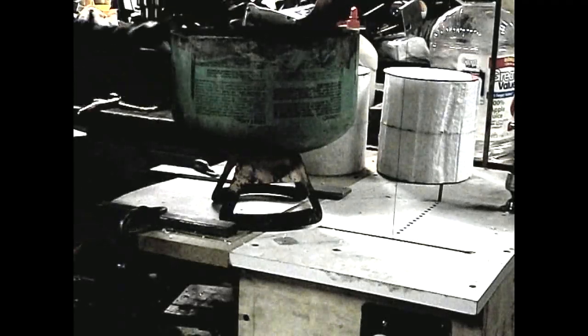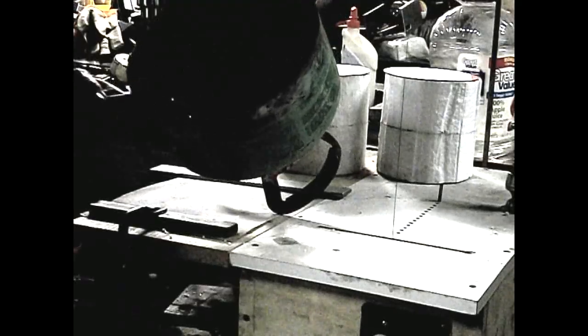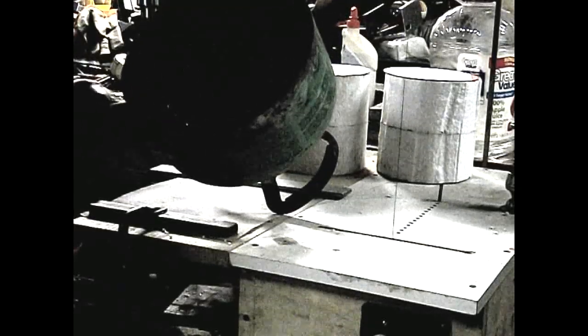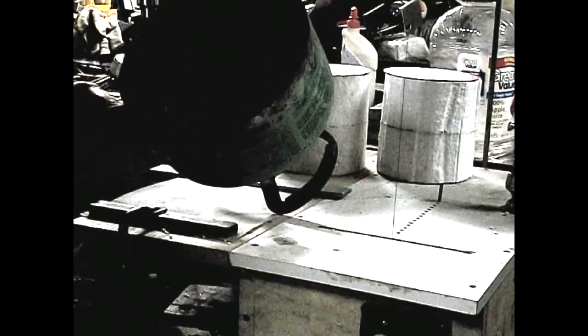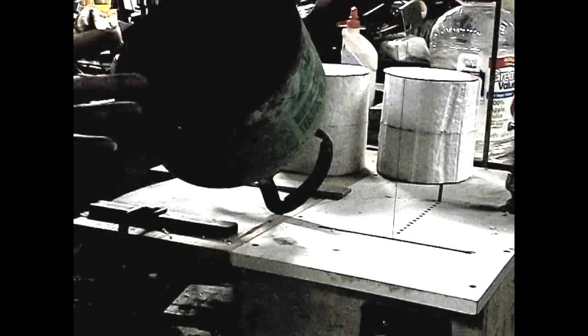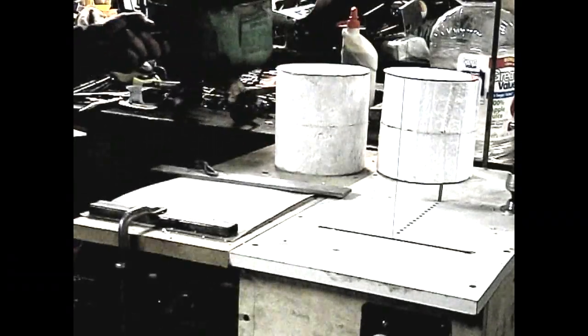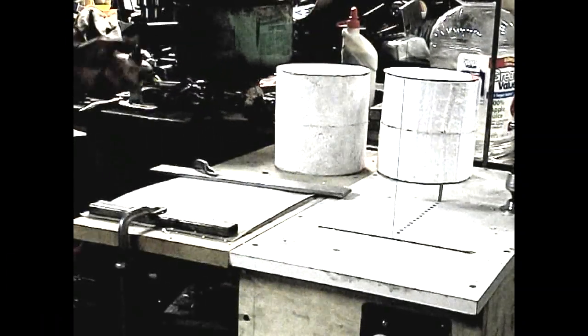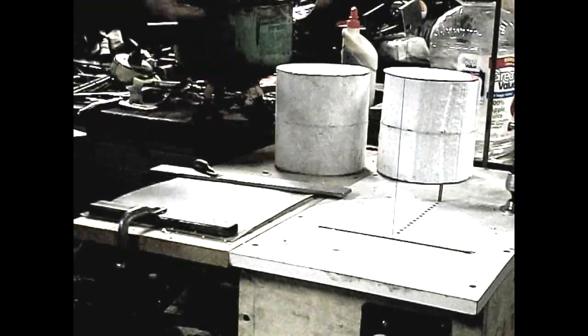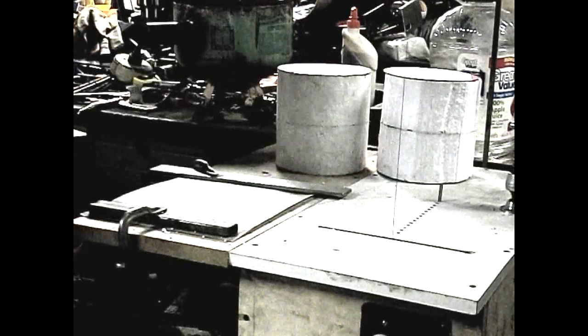Putting in the mold with spacers, and then I'll pack in the refractory. That's got to cure for three days to a week, depends on a lot of factors: how much water I use, how damp the surrounding area is. If it's real dry it'll dry faster, but it's got to be dry before you even fire it up. I'll come back when these are done and we'll start doing the refractory.